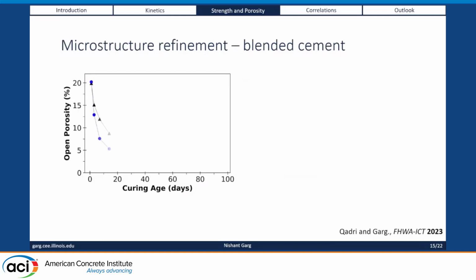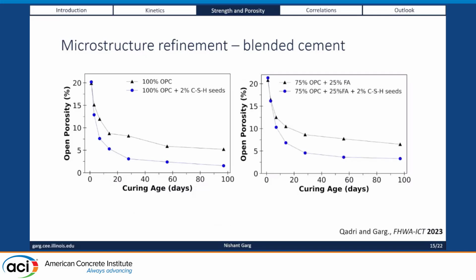And then if we look at some of the blended systems where you have OPC as well as the fly ash, again, we see this reduction in porosity, which was good. And again, all of this data is available in this report that came out last year along with the papers.